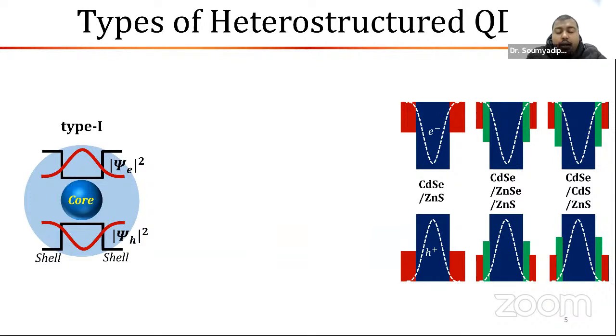Now, when we say quantum dot, a normal quantum dot has a problem. The problem is that bare quantum dots are not as stable as they should be, because there are surface traps and interactions with the surface. Therefore, without any protection, normal quantum dots are not that stable. So what people do is put a stable shell over the quantum dots to make them more stable.